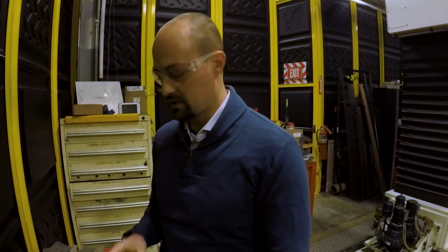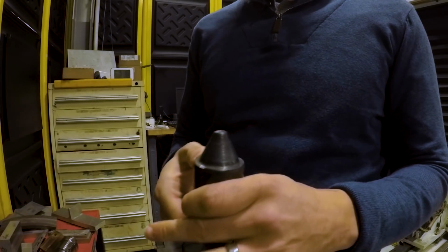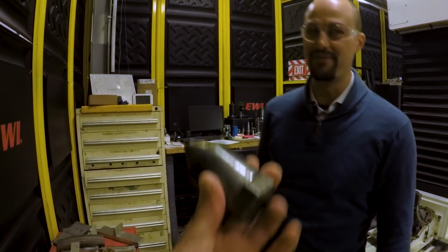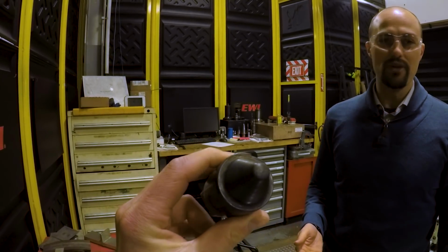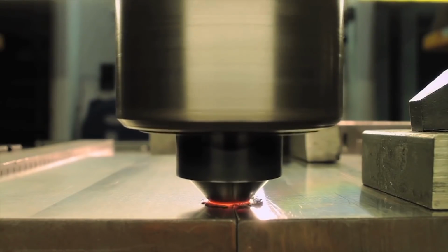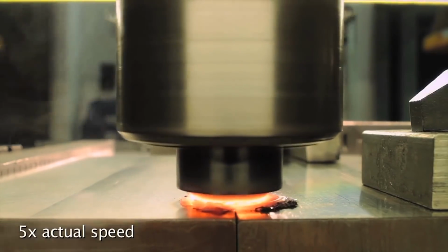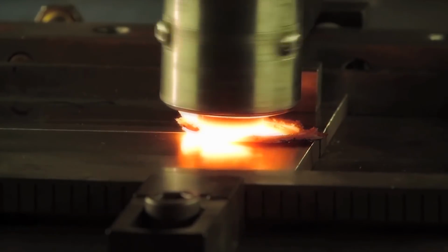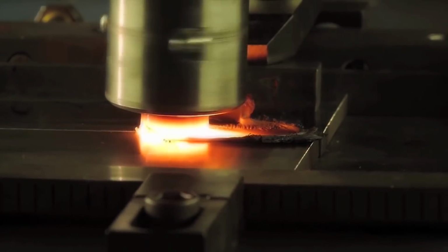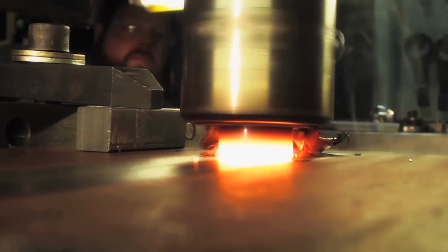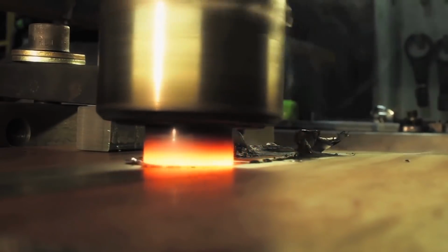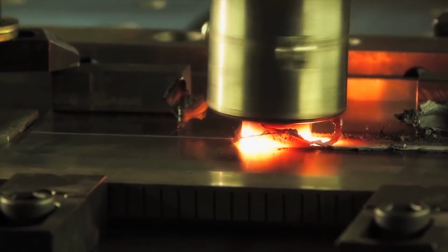When we get into steel, and this is where EWI really shines, we go to tungsten-based tool materials. Actually, put that in your hand. It's very, very heavy. And that is a few $1,000s an inch. Wow. Tungsten Rhenium Alloys Incorporated, up in Northern Ohio, specialize in making the material, and partnering with them, we can commercially buy those. We need tungsten because your melting temperature and your yield strength versus temperature curves really matter. With steel, we're getting up to 1200 C, 1400 C in order to stir this material. If we tried to use a tool steel, we'd be melting the tool as well. That's why we go to a tungsten-based tool material where your melting temperature is 3000 C, and you still have quite a bit of high temperature strength in that regime.